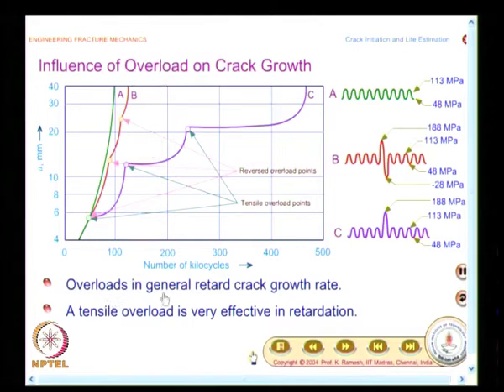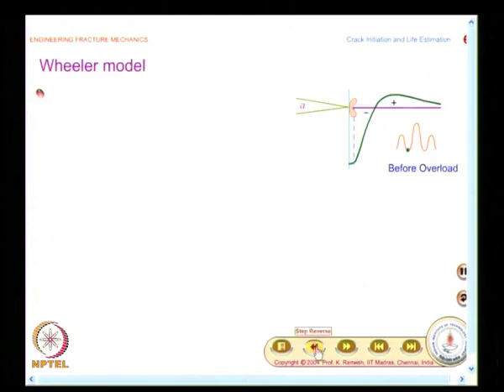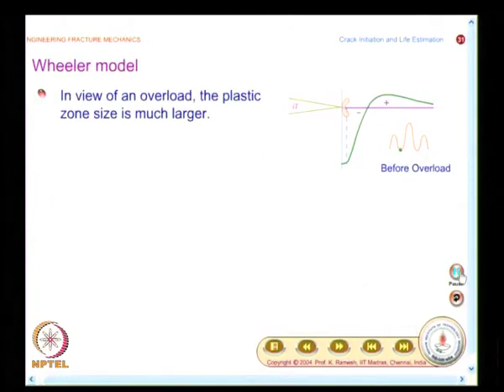And we would understand how the overloads in general retard crack growth by looking at the residual stress formation. And this is done by Wheeler, and he has given a model. So, what you will have to look at is, in view of an overload, the plastic zone size is much larger. I would repeat the animation.